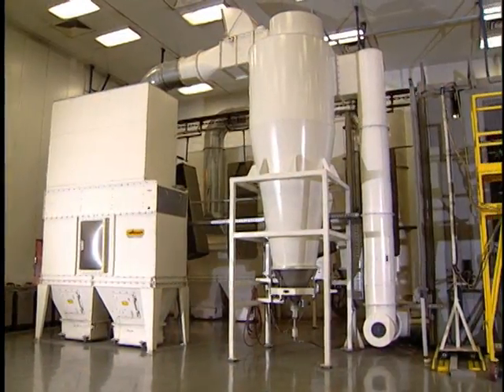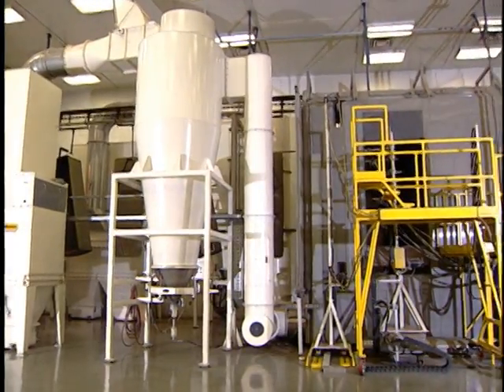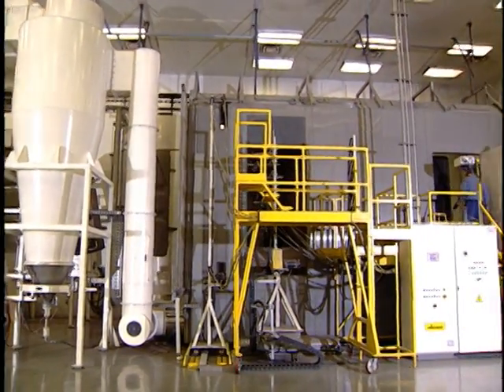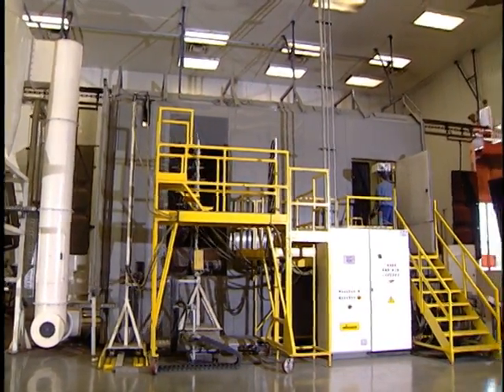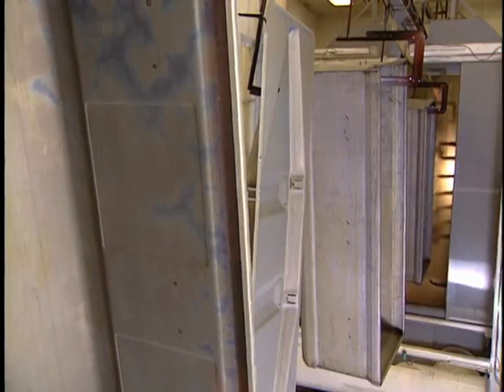The powder coating is then applied to the vault surfaces in a special clean room with precision temperature and humidity controls. Such strict control of environmental factors during application is critical as they affect the quality of the coating. Utilizing an electrostatic charge, 18 automatic guns apply the dry coating to each part inside and out. The initial application takes about 4.5 minutes to complete.